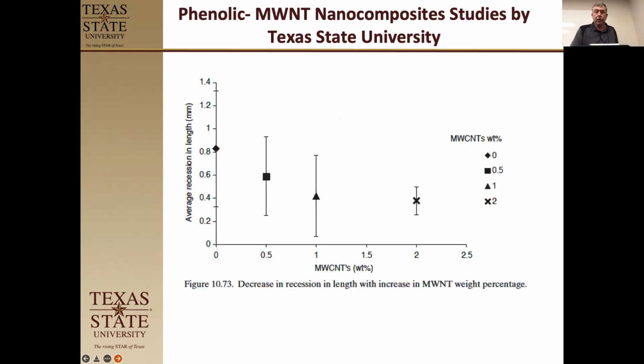So what they were looking for here is the average recession in length, which means how far it burned down in the system by adding carbon nanotubes. So right here is where we start with none. During the burn test, it burned down a little under a millimeter. Okay. And then by adding 0.5%, they have really wide error bars, but they averaged it out to 0.6. And then with 1%, you got even lower, but way over here, 2%, you have smaller error bars, and about the same as the loading. So overall, they think that the 2% is the right level for having this additive in their carbon phenolic composite.